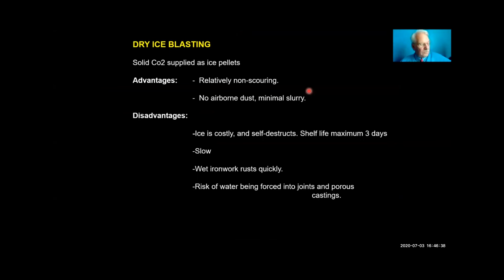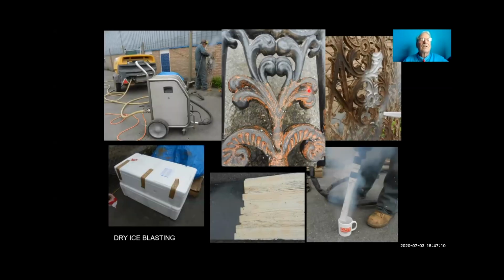Another of the modern processes you may have heard of, dry ice blasting, where solid carbon dioxide is used. It's relatively non-scouring, and there's again very little residue. The disadvantage is that the ice itself, of course, just melts within about 3 days. It self-destructs. It's a fairly slow process, and the ironwork rusts quite quickly afterwards once you've cleaned it. And again, you've got the problem of pushing water into the joints. So it's rather similar to dry abrasive blasting. It's just that you use dry ice. It goes into this pot here, a big compressor to drive it.